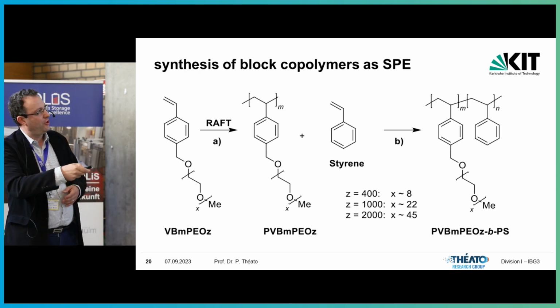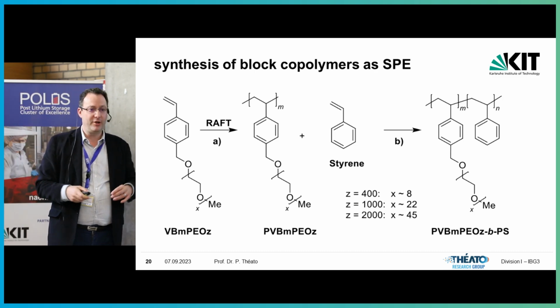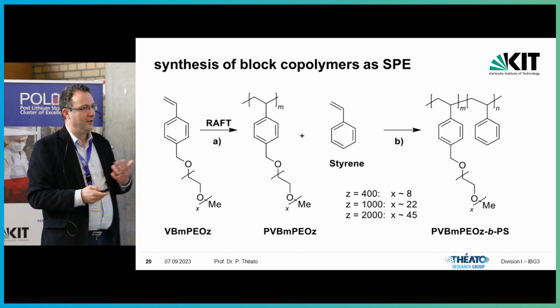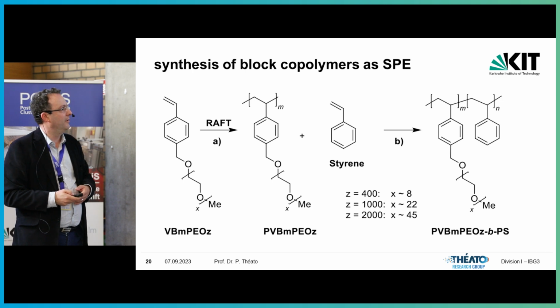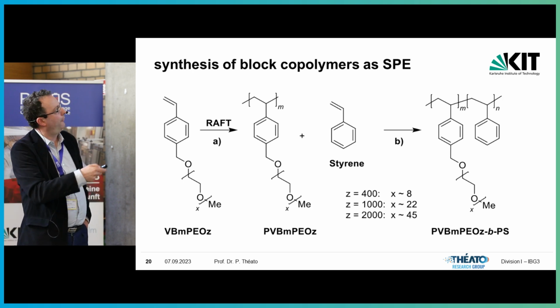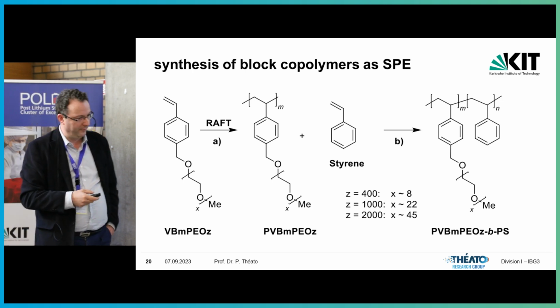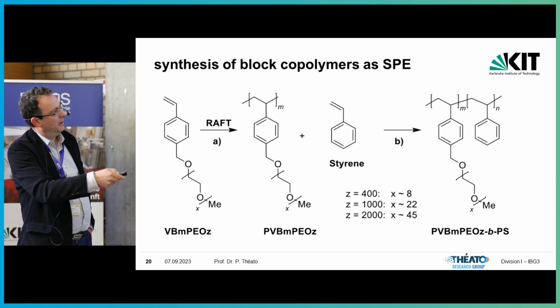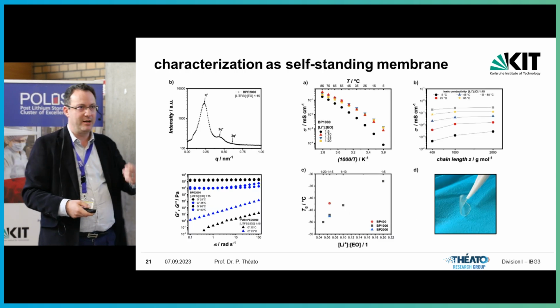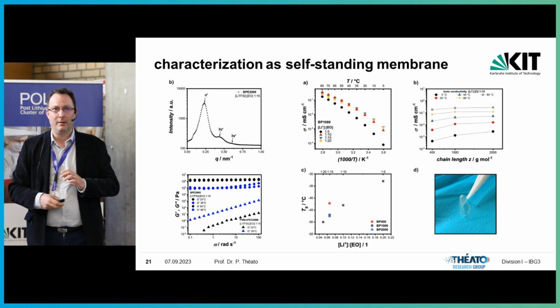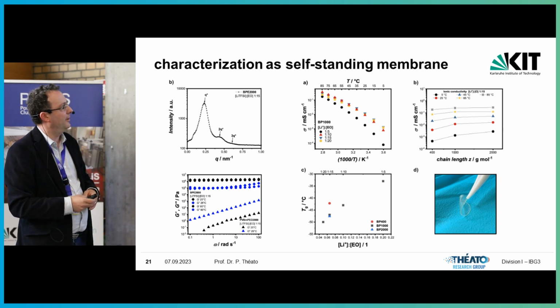We can play with the side chain lengths, but we need to make sure that the volume ratio of these blocks is about 50-50 so that we get a lamellar phase. We can confirm the lamellar phase, and it looks very nice from the scattering data here. This is how the film looks. So it's really a mechanically freestanding membrane without any other post-processing.